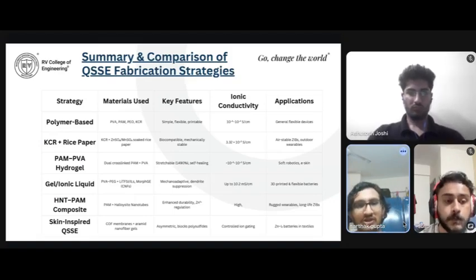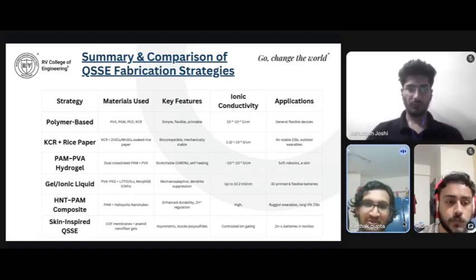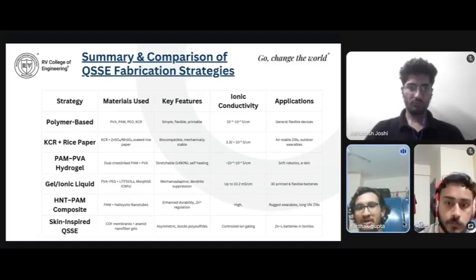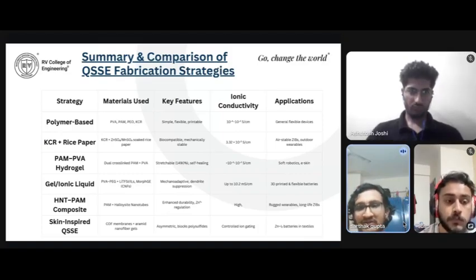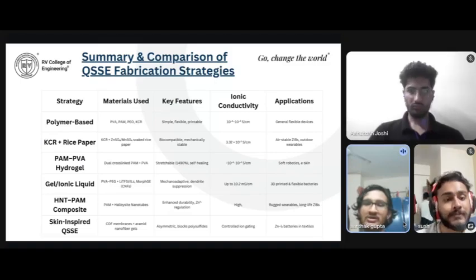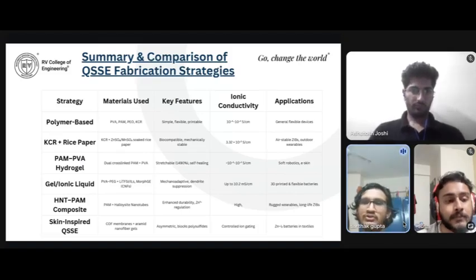PAM, PVA, hydrogel. This technique uses cross-linked PAM and PVA, as I mentioned, and it has a good stretchable part. Self-healing is one of the important features of this particular fabrication technique. It provides an ionic conductivity of approximately 10 to the minus 3 to 10 to the minus 2 Siemens per centimeter. Since it has self-healing and stretchable parts, it is highly applicable in soft robotics, or if you want any e-skin. E-skin is basically, if you want, let's say, prosthetic body parts, you can use it in that.